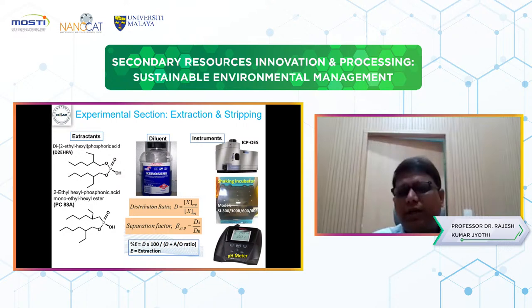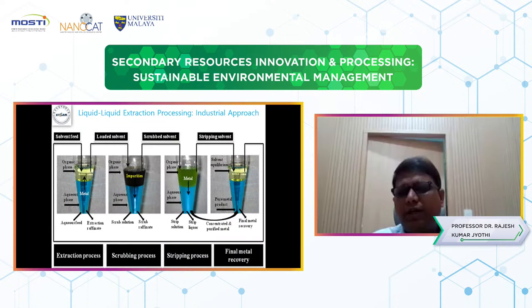The basic solvent extraction, liquid-liquid extraction industrial approach has four stages. One is the extraction process, second is the scrubbing process, third is the stripping process, and finally metal recovery. In the first stage, extraction, we target the metals; all the metals can extract, but sometimes unwanted metals are also co-extracted. Those co-extracted metals we can remove with water or base or very dilute acid. That stage is called the impurity removal stage, the scrubbing process. After scrubbing, the targeted metal can be recovered in the stripping stage. Once we strip out the metal, the pure solvent can be recycled again. So this is the liquid-liquid extraction process.